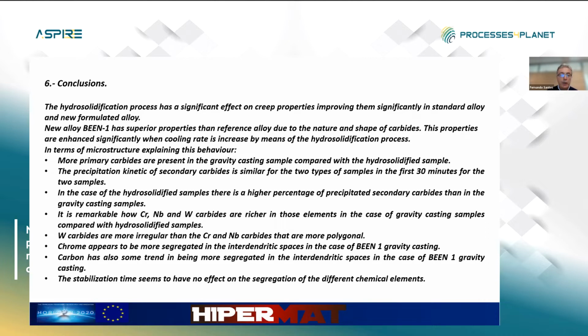And regarding microstructure, as we have seen, it's quite remarkable how primary carbides are present in the gravity casting sample in a high quantity compared with the hydrosolidified samples. The precipitation kinetic of secondary carbides is similar for the two types of samples in the first 30 minutes. In the case of the hydrosolidified samples, there is a higher percentage of precipitated secondary carbides.